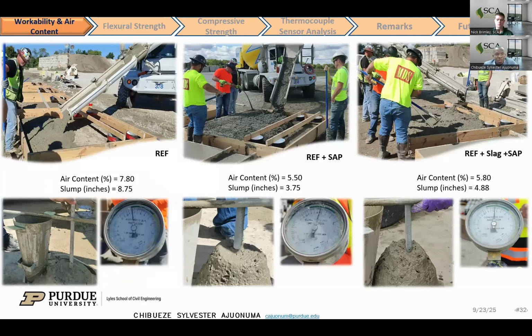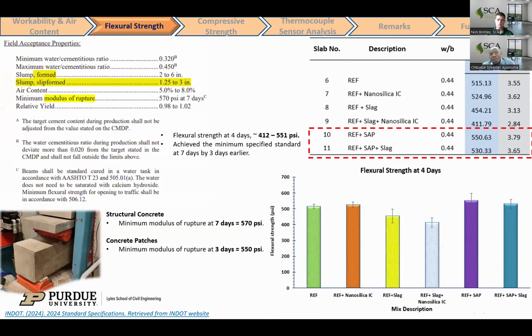Then these are some of the pictures from the field, showing the reduction in slump by the addition of SAP. And for flexural strength, the beams were tested at 4 days, because we're trying to evaluate how fast, if SAP was used in the field, the road can be opened to traffic.